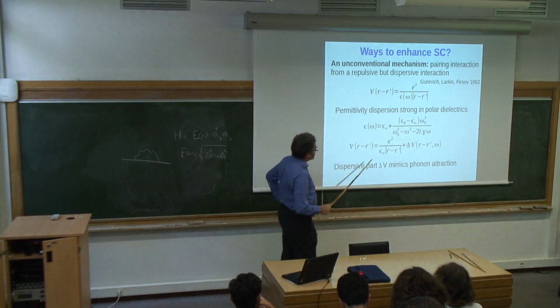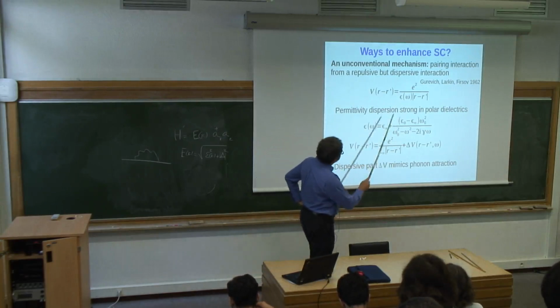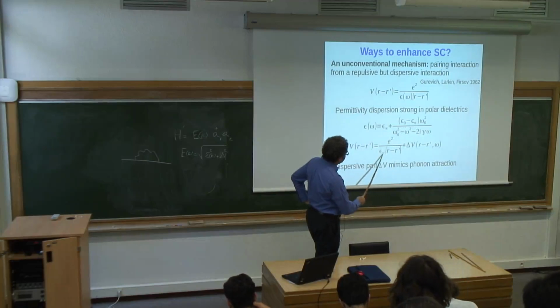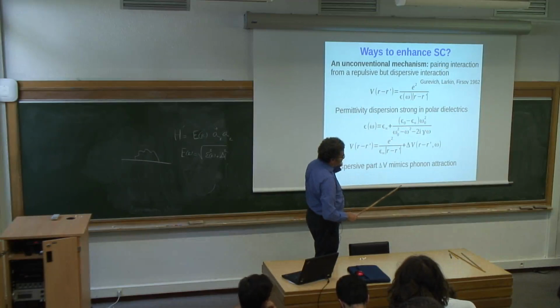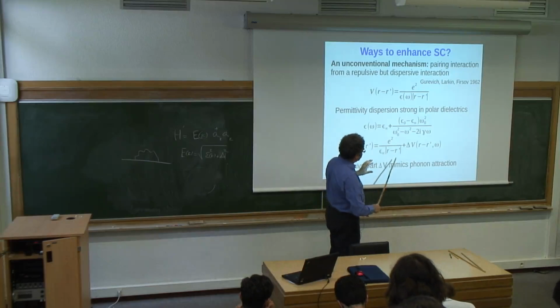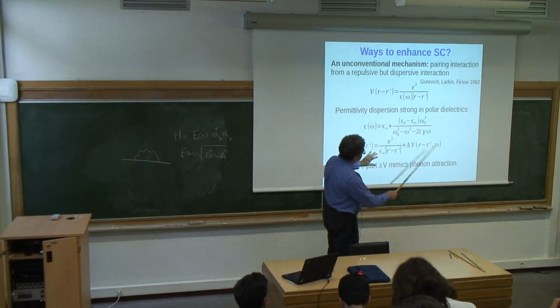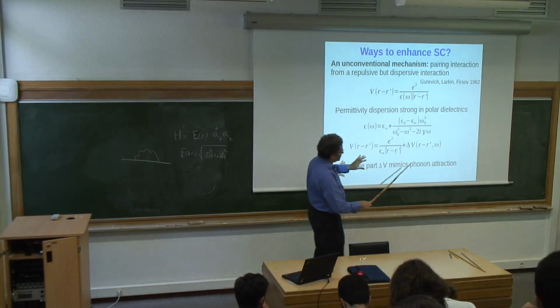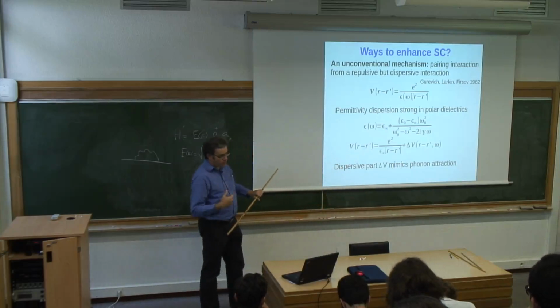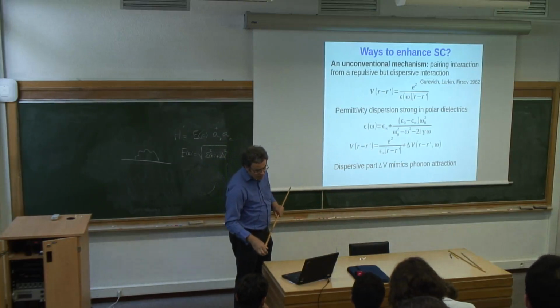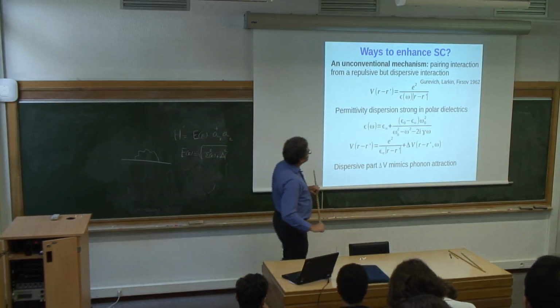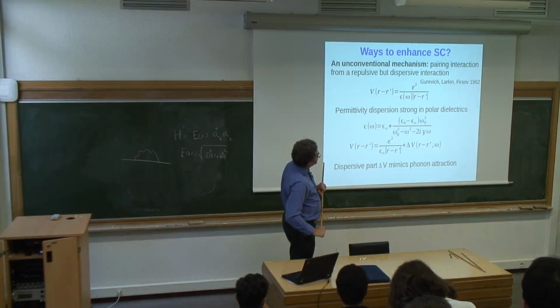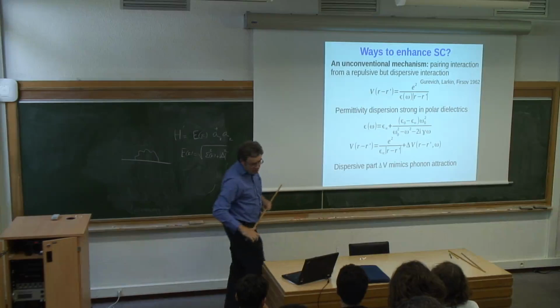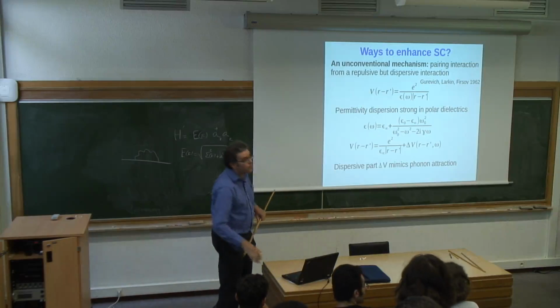And then you can show, as was done in this paper, that if you split this interaction into a non-dispersive part, determined by the value of epsilon above these vibrational resonances, and a dispersive part, then the non-dispersive part, which is repulsion, will play together with the dispersive part in the same way as Coulomb interactions play with electron-phonon attraction. You'll get superconductivity without explicitly introducing phonons into the picture, just via the dispersive character of permittivity.